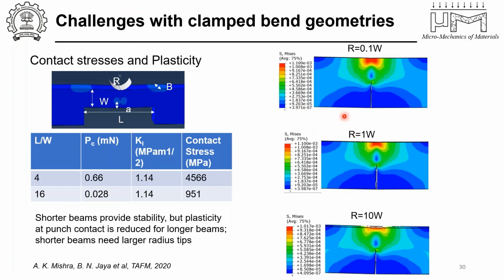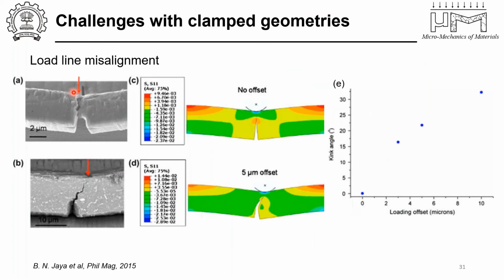But the problem with larger radius punches is that the alignment with respect to the crack length will then sort of go haywire, which is what I'm going to show next, because load line misalignment is another issue. If you have a misalignment with respect to the notch tip, then you will have mixed mode crack growth rather than mode 1. So you'll be measuring what is called mixed mode fracture toughness. But one can, of course, simulate or model this and look at the extent of K2 over K1 and be able to separate out the contributions from this.